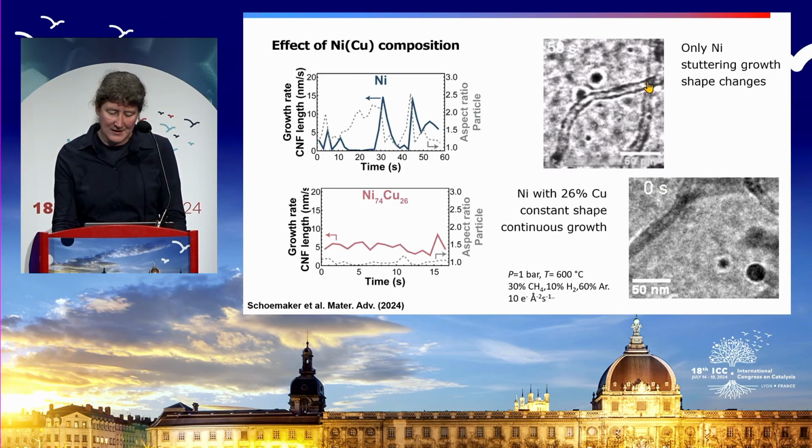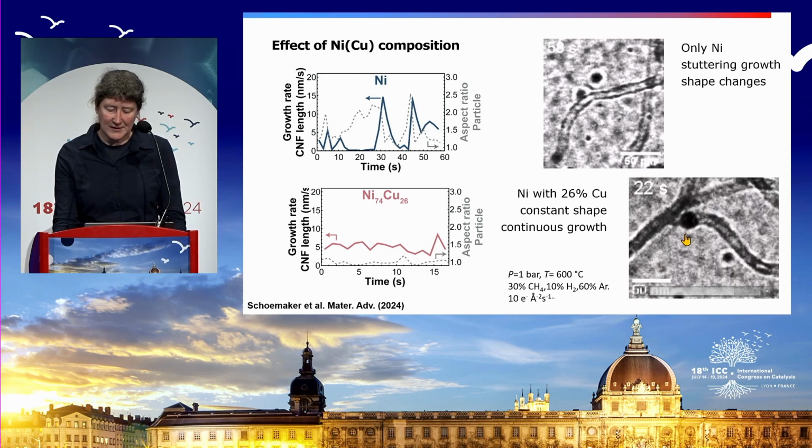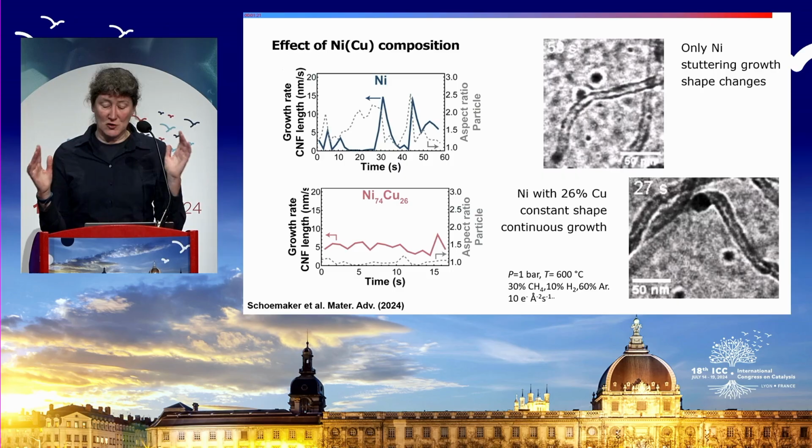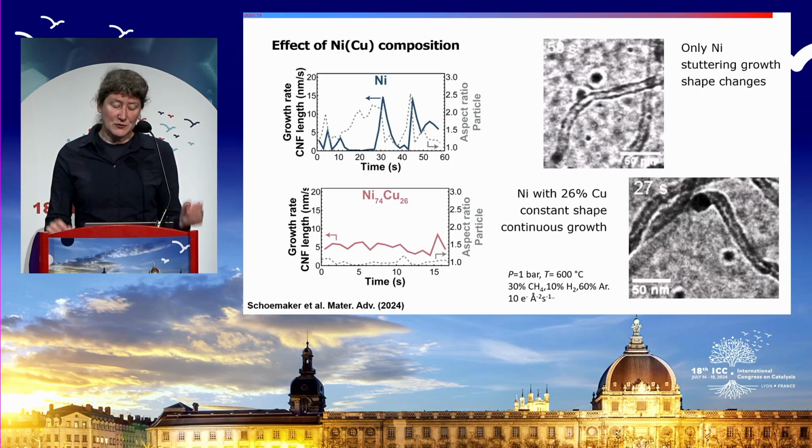And if you add some copper, you get a much more continuous growth, what you see here. And actually also the particle is much more spherical. It looks almost liquid, and it very continuously, with a continuous rate, will continue to grow the carbon.